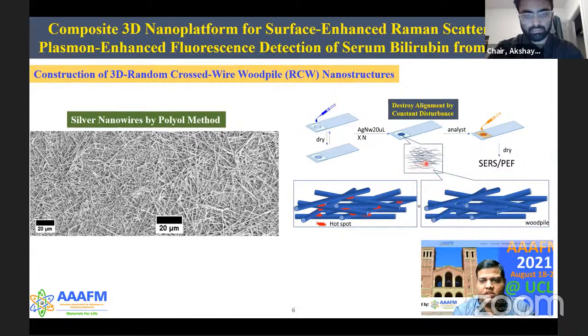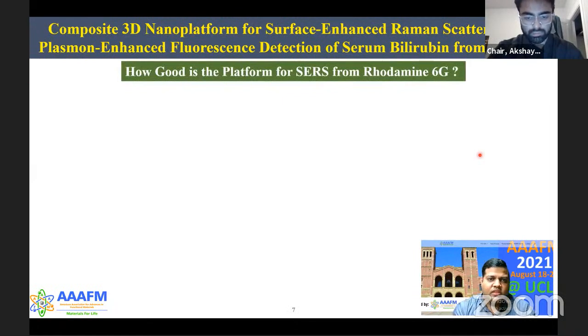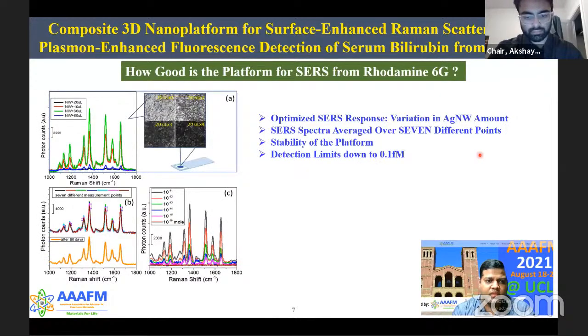And as the substrate is ready, the analytes can be drop cast onto the substrate, followed by vacuum drying, which can then be used as a SERS or PEF analytical platform. So to evaluate the efficiency of our SERS substrate created from the 3D nano platform, we used a standard molecule, R6G. So here is the SERS spectra obtained from R6G by variation in nanowire amounts. And we can see optimized SERS response can be achieved by variation in the silver nanowire amount.